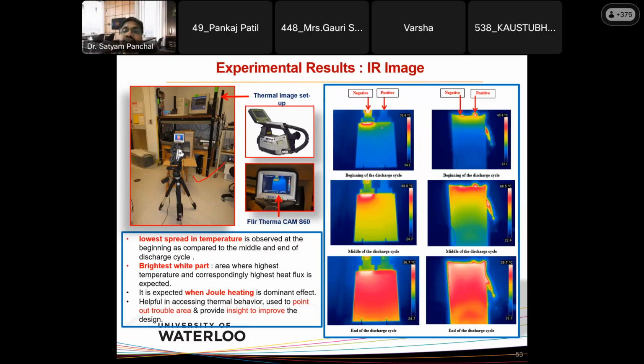I used that camera in order to get the IR images of the battery, in order to get the temperature distribution. Here you can see during the discharge of the battery, the current starts flowing, and this is the beginning of discharge, this is the middle of the discharge, and here you can see a completely red figure at the end of the discharge, with two different types of battery. Here you can see a smaller battery, 16 amp hour, and here a 20 amp hour battery. The whole purpose of this study is to find the lowest spread in temperature, and that is observed at the beginning as compared to the middle and end of the discharge.